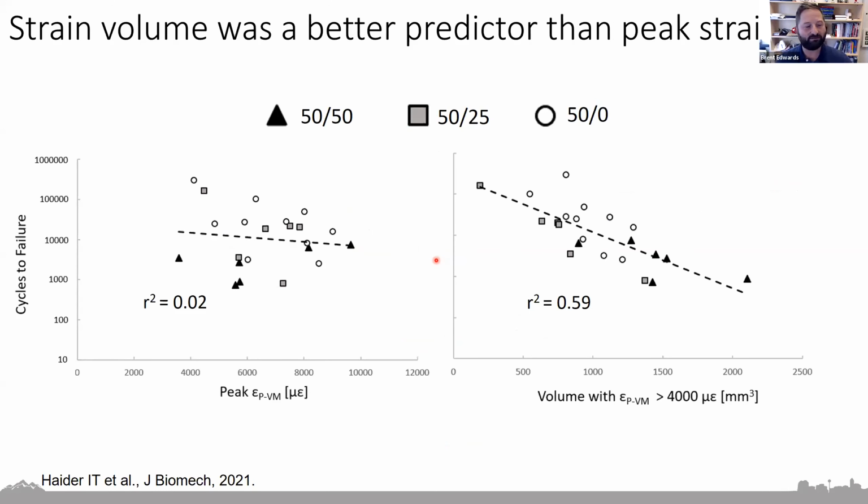So we looked at certain variables that we could pull from our finite element model. The first thing we looked at is what people do all the time when they try to create finite element models of the lower extremity and predict stress fracture risk. We looked at peak strain. This is the relationship between peak strain in the sample. In this case, it's a pressure modified von Mises strain, but it really wouldn't matter here if I put maximum principal strain or minimum principal strain. The peak strain experienced by the whole bone specimen is not a strong predictor of the fatigue failure of that